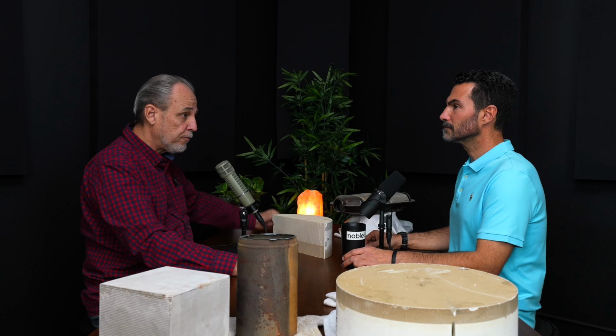Versus with the silicon carbide, you get the tarry mess in the furnace, and the tarry mess is going to hang on to metal. There's going to be losses to the flux, to the slag, of the platinum and the palladium. Right. And so the smelter can lose money. Yeah, absolutely. And that's lost in the slag. That's the main reason that the smelters don't want to see much silicon carbide mixed in with the AutoCat coming into their operations, because of the losses they experience to the slag.